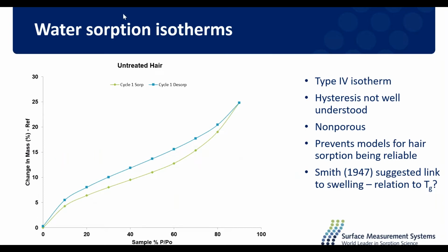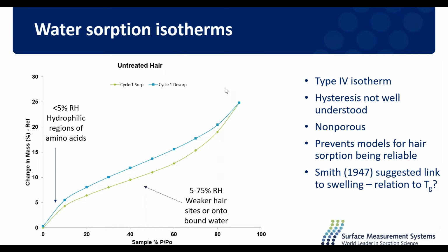So here is a water sorption isotherm for untreated hair, and we can learn a lot just from this sorption isotherm. It has a type 4 character with a characteristic hysteresis. It's well understood that at low relative humidities, water will bind first to hydrophilic regions of the amino acids. At intermediate relative humidities, it will bind to weaker binding sites on the amino acids and also to those previously bound water molecules. At high relative humidities, clusters begin to form. And we can see that they absorb quite a lot of water, about 25% per weight.